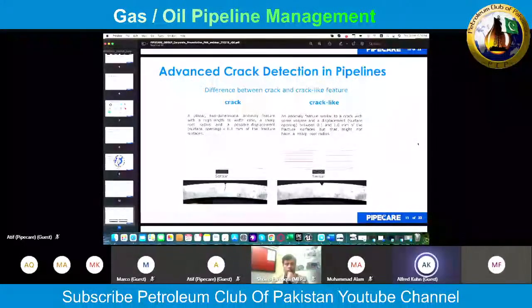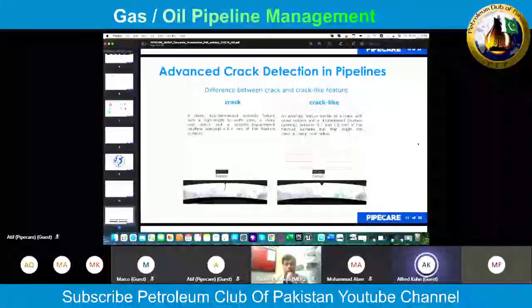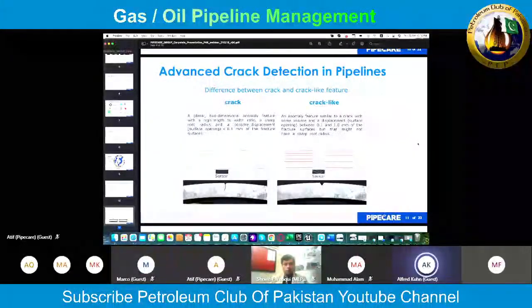You see a drawing where a crack is indicated, and this may even still be closed, so no opening at all. What you also see are some lines, and these lines represent the magnetic lines of a magnetic tool which passes this crack. The magnetic field just passes through that crack without being deflected. Whereas if we look at the crack-like feature, which has a similar definition but different opening dimensions, between 0.1 and 1 millimeter opening of the fracture surface, this is enough to deflect the magnetic field and give an indication to the sensor of a magnetic tool.